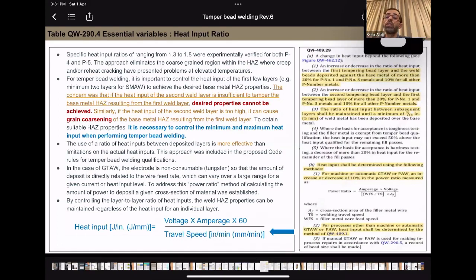So what we are doing is that we have a heat input ratio between any weld and the subsequent weld run, and normally it is 1.3 to 1.8, developed and proven for P4 and P5A material to control the hardness and the toughness of the weld. So heat input is not the factor that controls the mechanical properties of the base metal or heat affected zone when using temper bead. Rather, it is the heat input ratio.